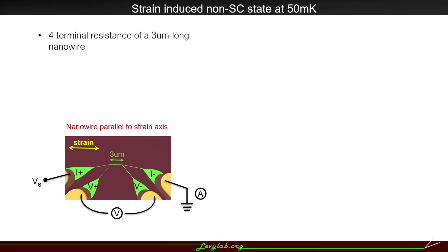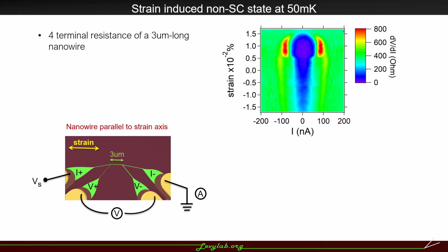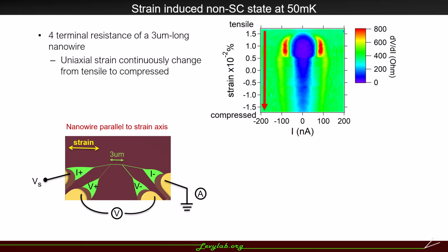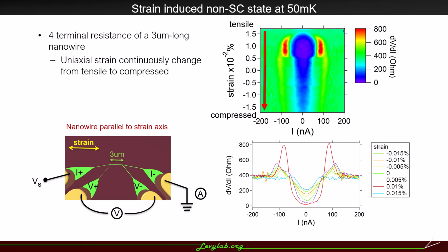This page shows result of our 4-terminal resistance of a 3 micrometer long nanowire. It is aligned with uniaxial strain direction. We plot resistance as a function of current and strain. This data is taken when we continuously change the uniaxial strain from tensile to compressed. To see the features better, we plotted line cuts of the intensity graph at some strain values. You can see the purple colored regions, which is superconducting state, and the corresponding superconducting gap. But there are also some strain-induced non-superconducting states. We observe the smooth change in superconducting critical current.